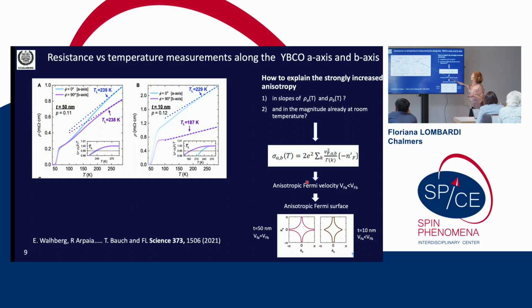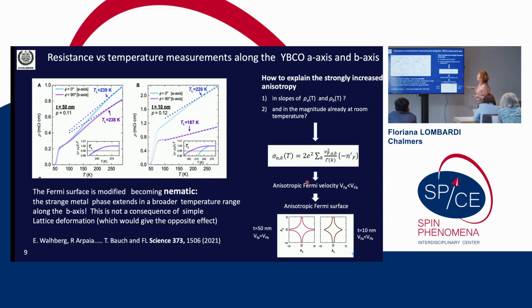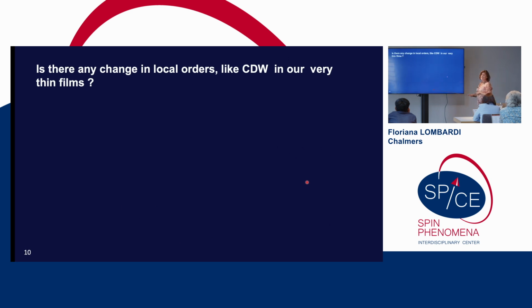But if you have the same doping and you go to 10 nanometers, physics changes dramatically. So you have a strong anisotropy in resistivity, even at room temperature. You have that the strange metal in the B direction extends to much lower temperature, but very significantly here are the slopes in the two resistive transitions. They are very different. And if you take the Boltzmann formalism, you get that the Fermi velocities along A and B become different. So you go from this circular Fermi surface to a nematic Fermi surface. And this nematic Fermi surface, most probably, is the origin for all this, as I will try to convince you later on. So this is simple transport.